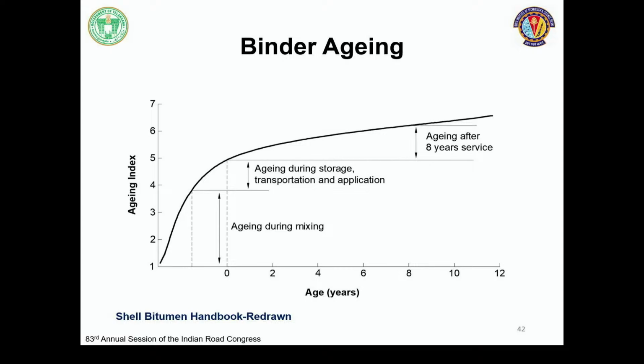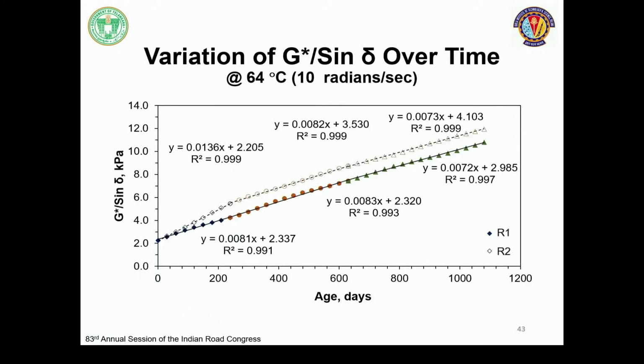And also the Shell Bitumen Handbook mentions a lot about this aging, initial aging, which Praveen Sir mentioned, that is short-term aging, and then the long-term aging. But the rate of aging depends on the air voids. This is with an assumption that the air voids is 7%. But if the air voids is quite high, the rate of aging is different from what is shown in the Shell Bitumen Handbook. It may not reach it by 8 years, probably we'll reach it by 4 years. That is what our data showed.